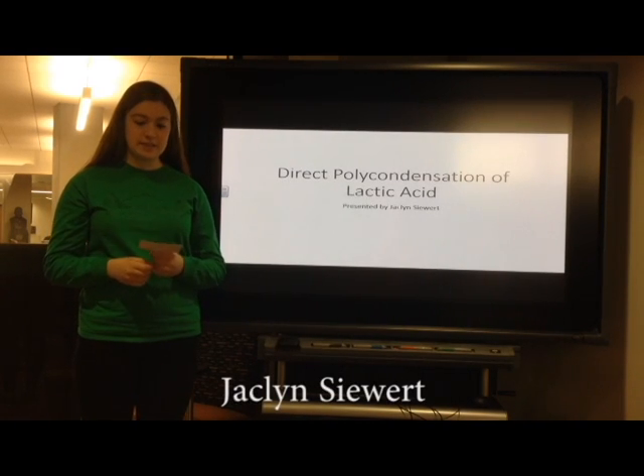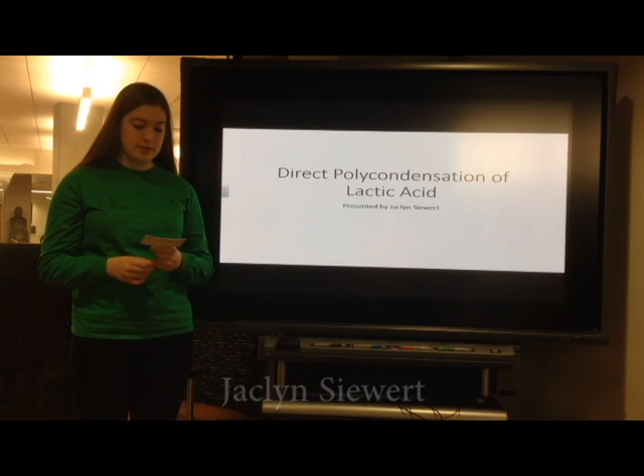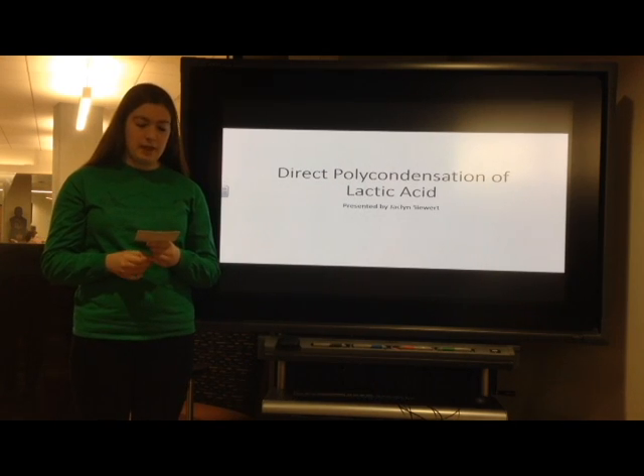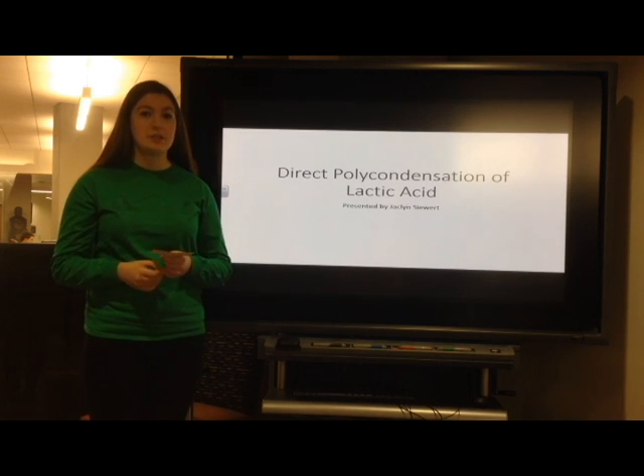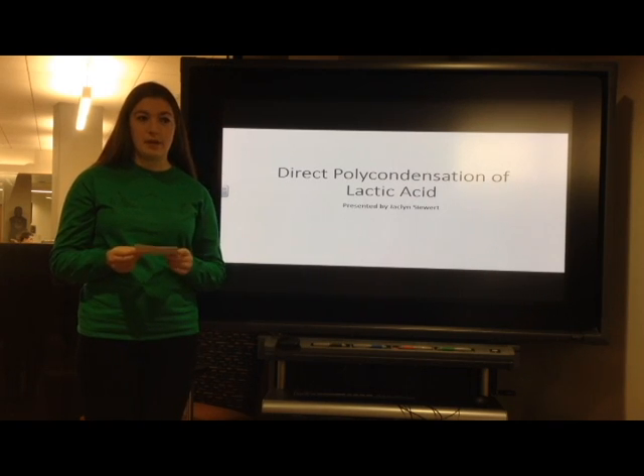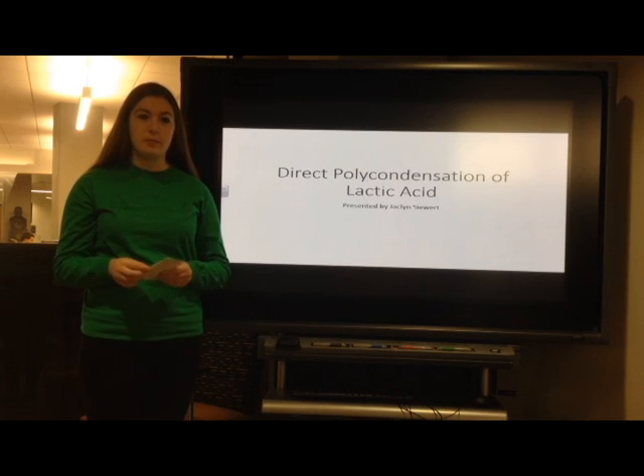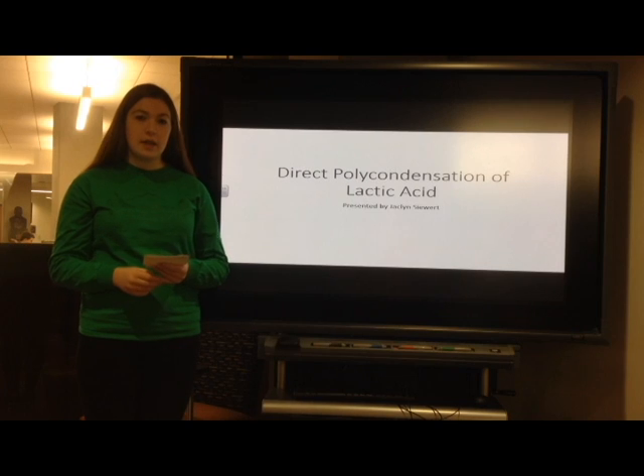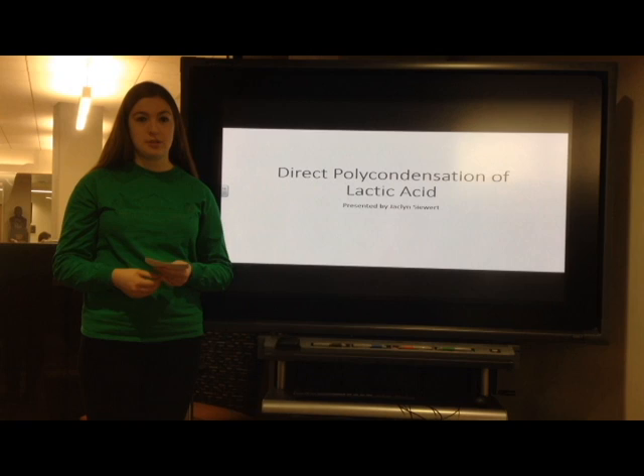Now here's Jaclyn to talk about another method: polymerization by polycondensation of lactic acid. In the direct polycondensation of lactic acid, two stereoisomers can be used. Polylactic acid synthesized by this method can include both stereoisomers, just one, or in combination with other hydroxyl acids. Polylactic acid produced by direct polycondensation usually has a low molecular weight, which is not optimal for load-bearing medical applications, but it can be used in areas where chemical properties are more important, such as in coating techniques and tissue adhesives.